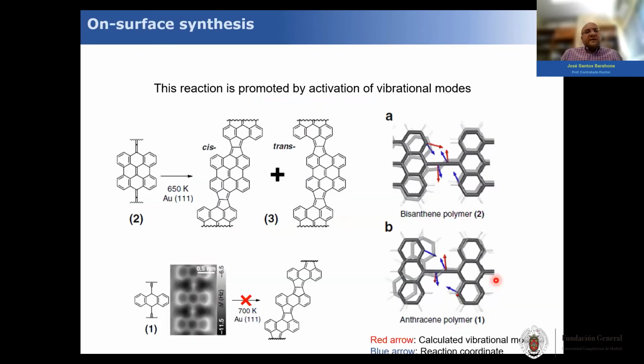And how do we explain this transformation? This is quite interesting, because we compared this with anthracene, and we tried to do the same, and nothing happened. Whereas in the case of the Pentacene, we also have similar results as this one. So how could we explain that for the longer ones the reaction works, and for the anthracene, the aromatic ones, it doesn't?